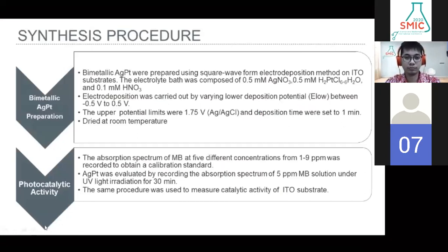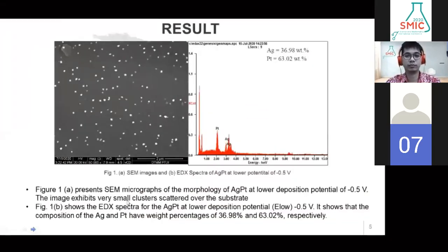Okay, next is the result. Here's the result of the SEM micrograph of the morphology of AgPt at lower deposition potential, or ELO, at minus 0.5 volt. You can see that the image exhibits very small clusters scattered over the substrate. And Figure 1b shows the EDX spectra for the AgPt at ELO minus 0.5 volt, and it shows that the composition of the AgPt has weight percentages of 36 and 63 respectively.